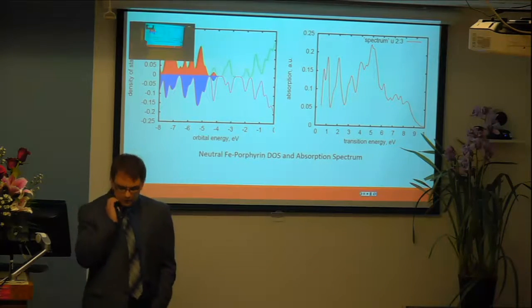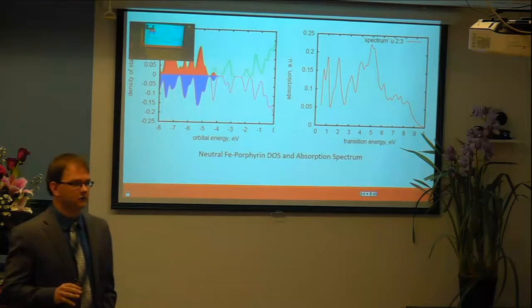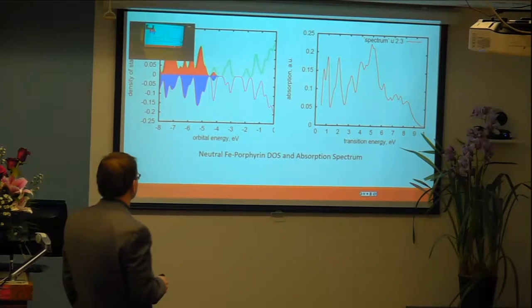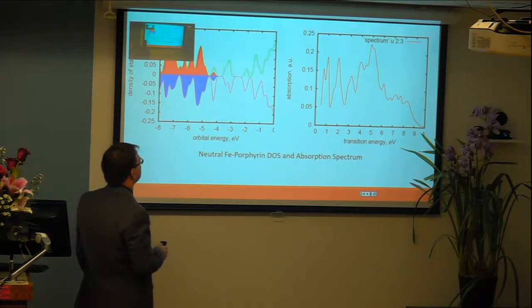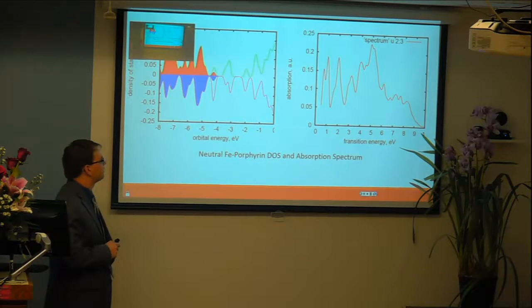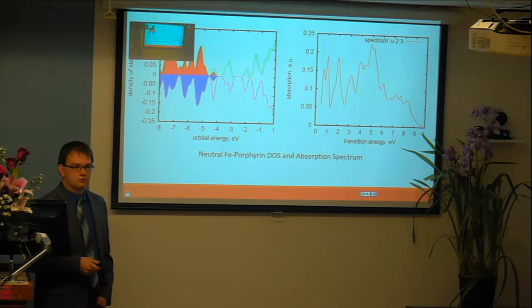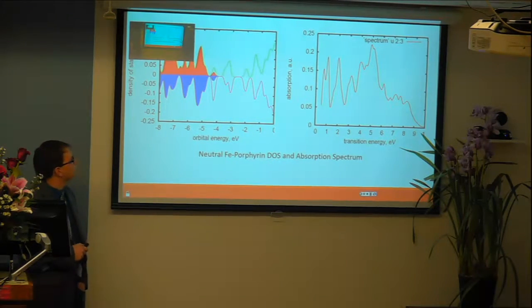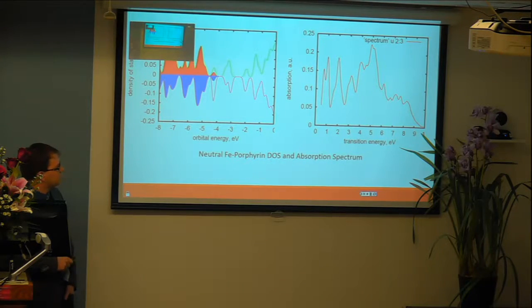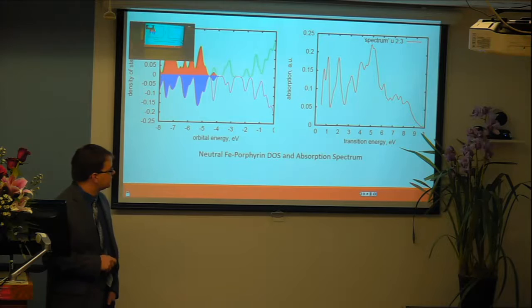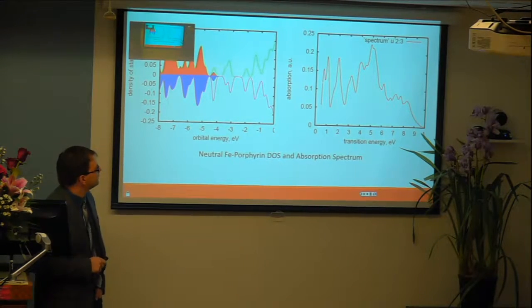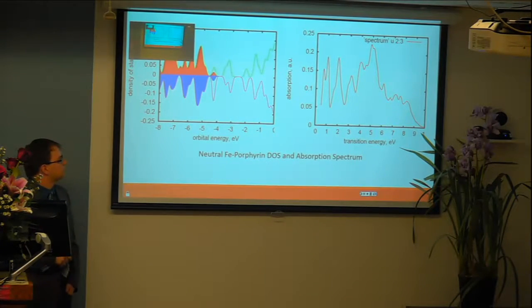Well, we can calculate just the macrocycle by itself, and we get a structure that looks something like this. You have partially spin up, partially spin down occupied states. Since we do spin polarized calculations, we have the ability to do that. If you analyze this absorption spectra, you can pick out some peaks that are indicative of, say, porphyrin rings, but I haven't done too much analysis into that for this purpose.